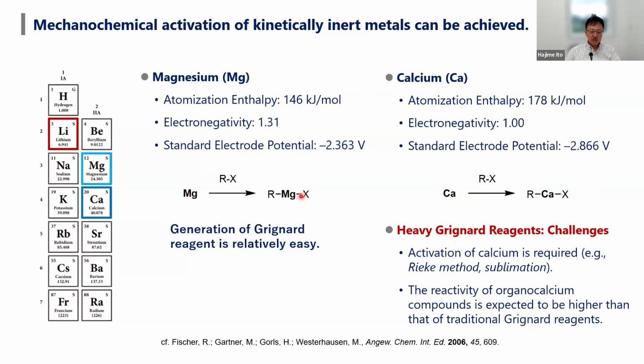For Grignard reagent synthesis, you can just mix magnesium and alkyl halide in solution or by ball milling. But calcium is very stable compared to magnesium metal—just mixing calcium and organic halide did not produce calcium reagents.